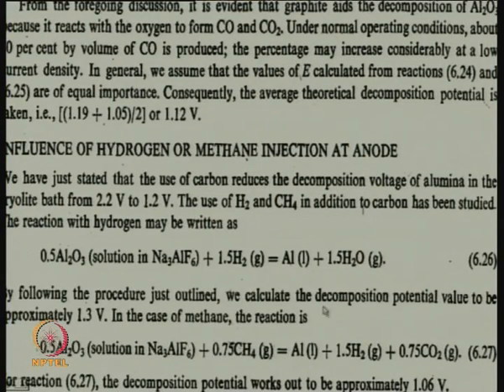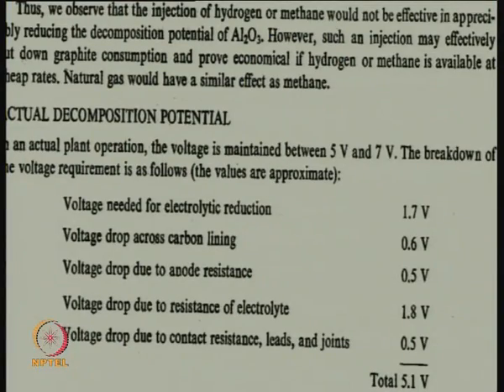The other idea could be injection of methane. You can calculate what the decomposition potential will be if you allow the oxygen that is coming out to react with methane. So, the overall reaction is this, and you get hydrogen and CO2. This works out to 1.06 volts. So, there is not really an advantage. First of all, technologically these may not be feasible. You cannot inject hydrogen at this high temperature into a cell; you can have an explosion. But it is interesting to look at the theory. These could be ways of lowering the consumption of graphite if you can inject methane or hydrogen, but nobody would like to try it out.